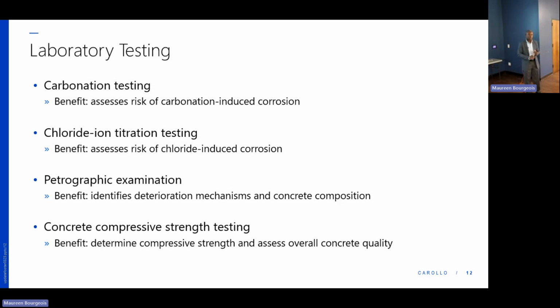What type of aggregate was used? What type of sand was used? Did they use any of what we call supplementary cement materials like fly ash? We can see that under a microscope. And then more importantly, there are some cracks that are not visible to the naked eye. Do we see that under the microscope? Because eventually those will deteriorate the concrete. And so we want to do that with a petrographic examination under a microscope.